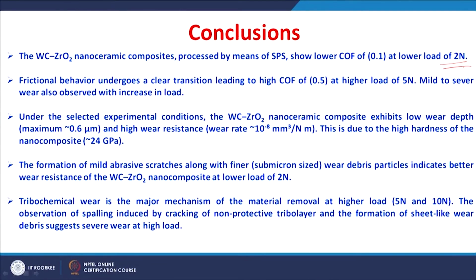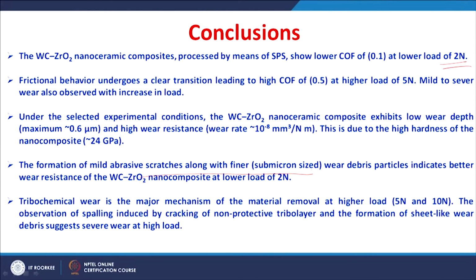Under the selected fretting wear conditions, the tungsten carbide zirconia nanoceramic composite exhibits lower wear depth and higher wear resistance because of the hardness of the nanocomposite, which is around 24 gigapascal. The formation of mild abrasion scratches along with finer sized debris indicates better wear resistance of the composite at the lower load, whereas at a higher load of 5 Newton or more, tribochemical wear is the dominant mechanism of material removal. The observation of spalling induced by the cracking of this non-protective tribolayer and the formation of sheet-like debris also suggest severe wear at the higher load.